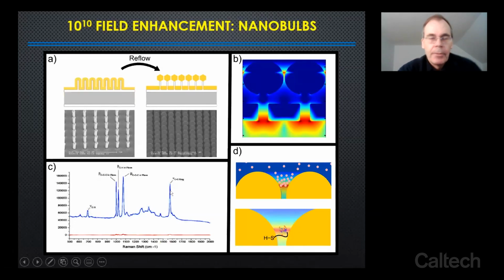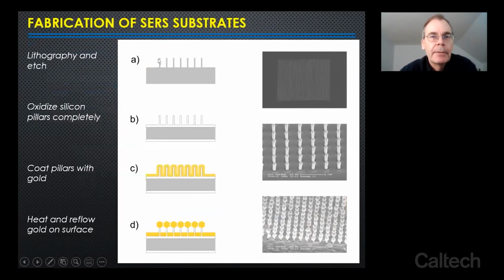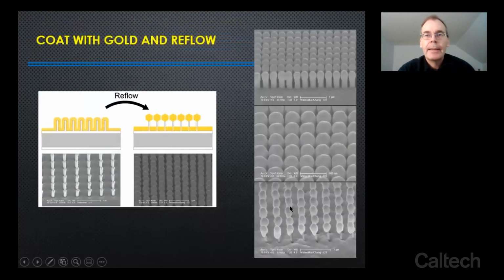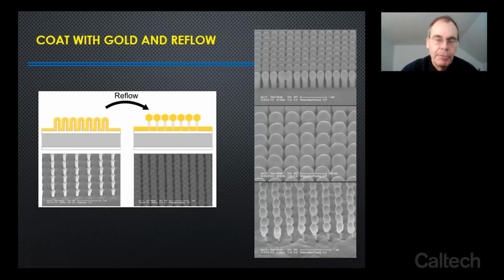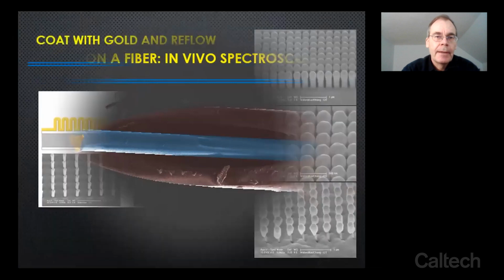And so the way that we make these little nanobulbs is by using microfabrication. So we make little silicon pillars. We oxidize those so they become silicon dioxide. Then we coat them with gold, and then we heat this up. And what happens is the gold diffuses, and surface tension forces it to become sort of rounded and forces these tiny little bulbs to occur. And then as you make them bigger, as you wait longer, you generate this surface of very uniform gold balls that have these very high field enhancements. As you reflow the gold, you generate these high fields.